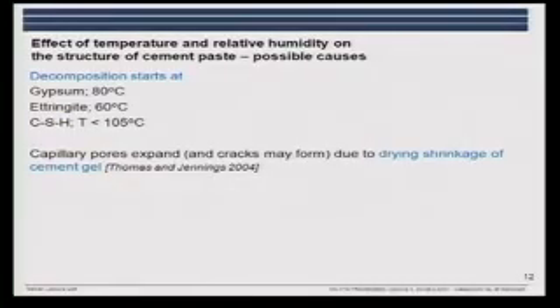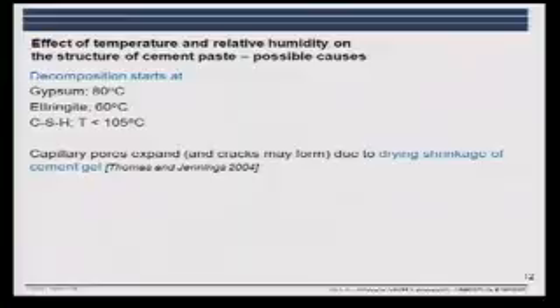So this was drying. We could also dry by heating the sample. And you can see here that if we heat the sample, some of the phases in the system start to decompose, like the gypsum. For instance, if we were drying at 105, which we saw was used for the data giving the background for Power's model, we can see that we have gypsum and ettringite starting to decompose, and also the C-S-H. And in addition, we may have some crack formation.